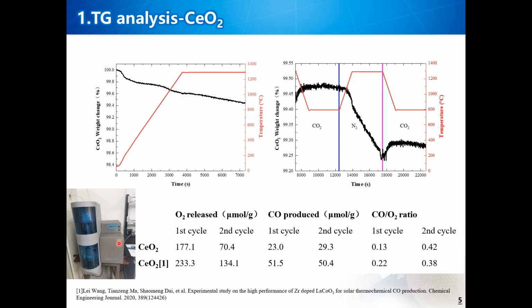This is our TG device. First, we test and compare the cerium dioxide material that was easily available in the paper. We weighed 15 milligrams of cerium dioxide and placed it in the alumina crucible. The reduction temperature was 1030, and the oxidation temperature was 800, which proved to be more suitable temperatures in subsequent experiments. The carrier gas in different stages is nitrogen and carbon dioxide with a flow rate of 20 SCCM.